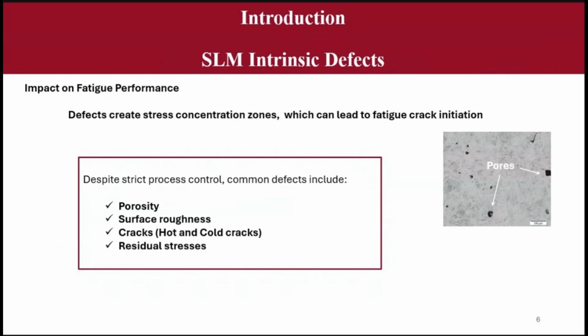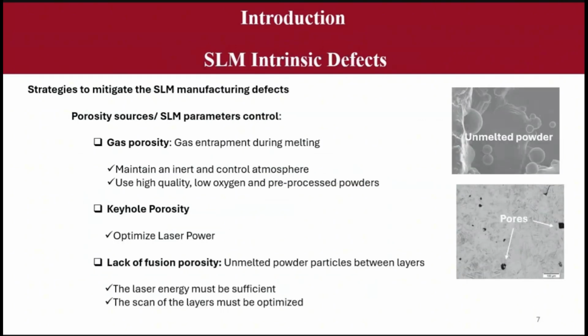All of us know that defects create stress concentration zones, which can lead to fatigue crack initiation. So we have to study these defects. Despite strict process control, common defects include porosity, surface roughness, cracks, hot or cold cracks, and residual stress. And of course, we already know how to control the SLM parameters to mitigate the SLM manufacturing defects. For gas porosity, we can maintain an inert and controlled atmosphere, and use high quality, low oxygen, and pre-processed powder. For keyhole porosity, we can optimize the laser power, and for lack of fusion porosity, the laser energy must be sufficient and the scan of the layers must be optimized.